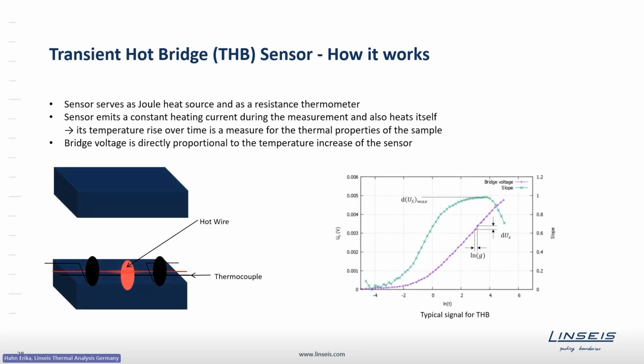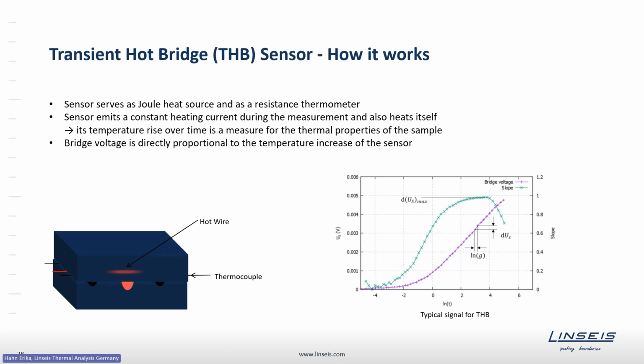Here you see again this measurement principle where the sensor serves as a Joule heat source and a resistance thermometer. During the measurement, the sensor emits a constant heating current and also heats itself. The temperature rise over time is then a measure for the thermal properties of the material, where I look at the bridge voltage, as this is directly proportional to the temperature increase of the sensor.